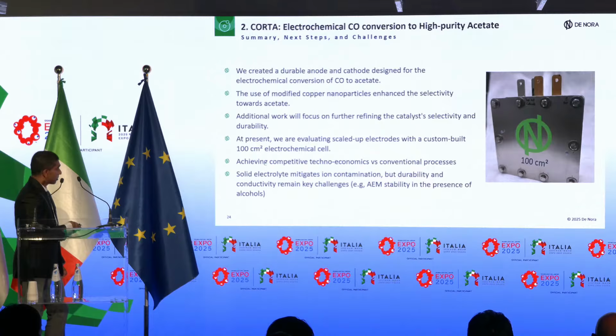The last thing I want to mention: even though the solid electrolyte mitigates the ion contamination, there are other challenges in this system. For example, when you use copper-type catalyst, it also generates some ethanol, which can be very harsh on the anion exchange membrane. So it significantly reduces the stability of the membrane. There are a lot of design principles that we need to use when designing these components to keep running the cell for longer duration.